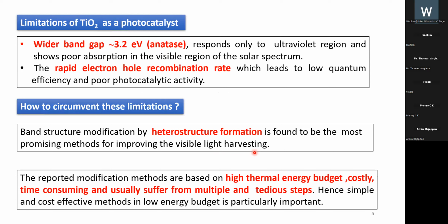The three most common polymorphs of TiO2 are anatase, rutile, and brookite. Anatase TiO2 is an n-type indirect bandgap semiconductor with a bandgap of 3.2 electron volt, which is used in charge separation devices like DSSCs and photocatalysis. However, due to its wider bandgap of 3.2 electron volt, it shows poor response to visible light absorption. Also, its fast electron-hole recombination rate leads to poor quantum efficiency.